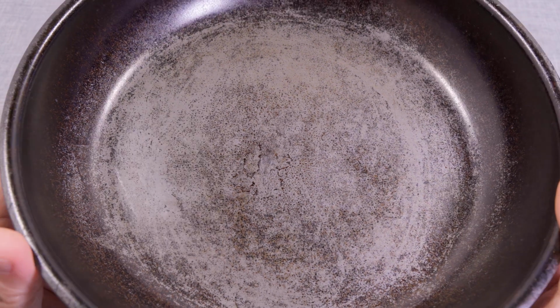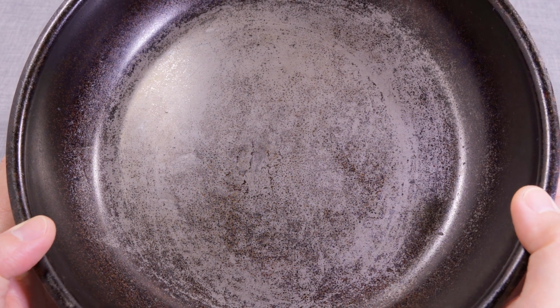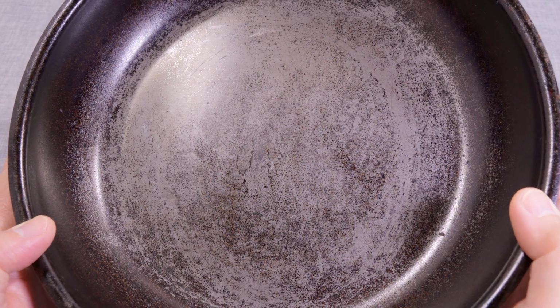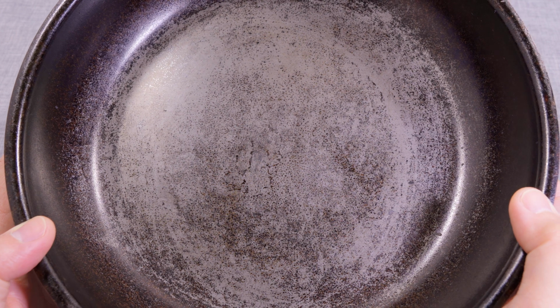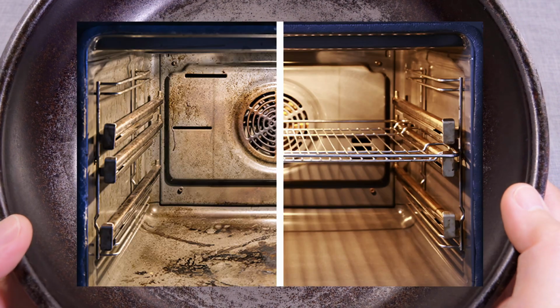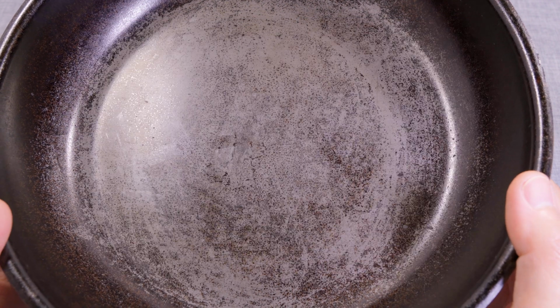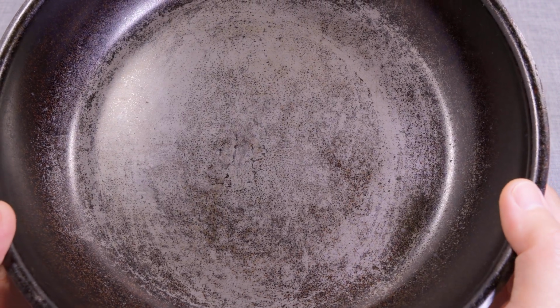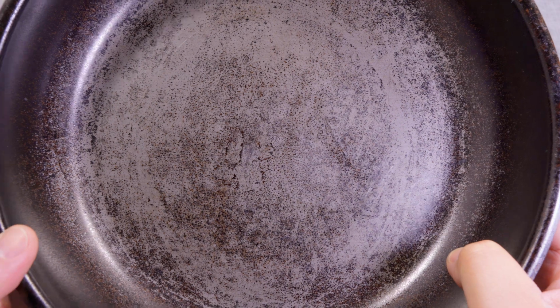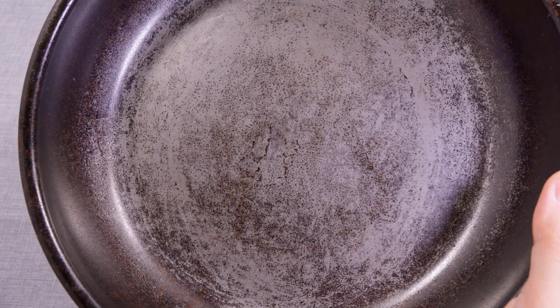Alright, so let's think about this more. If we use the current process of 500 degrees for 1 hour, then by the end of a 6-layer seasoning, that first layer would have endured 6 hours of 500 degree temps from direct contact with the aluminum. If you look at how grease carbonizes after a 4 to 5 hour oven self-cleaning cycle, you kind of see where I'm going with this. What we're really producing with this process is 3 layers of extremely carbonized oil, and probably only the last 2 to 3 layers that's actually polymerized. Could this be the reason it washed off so easily?